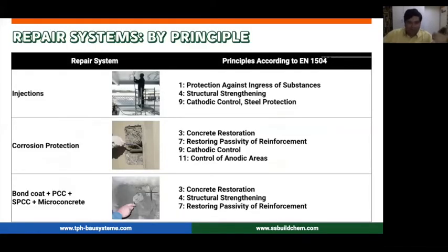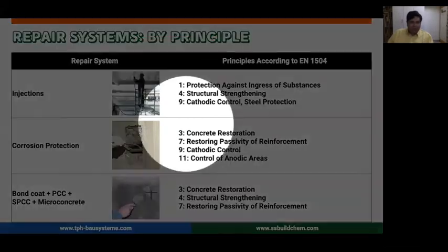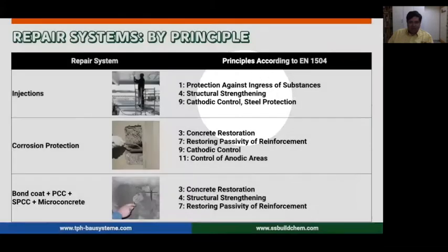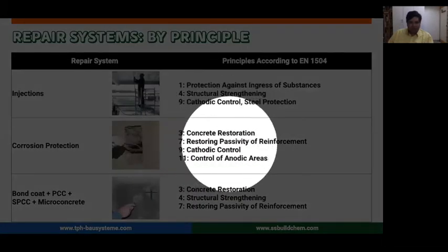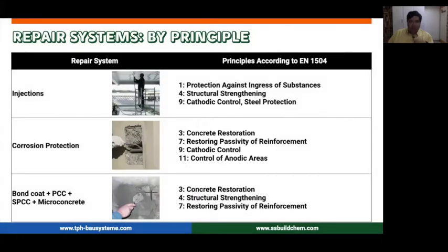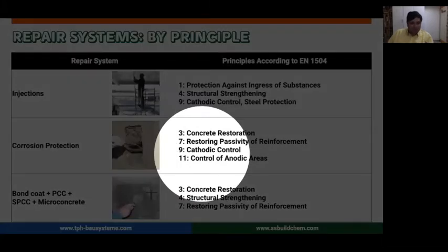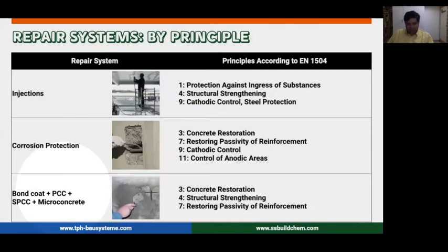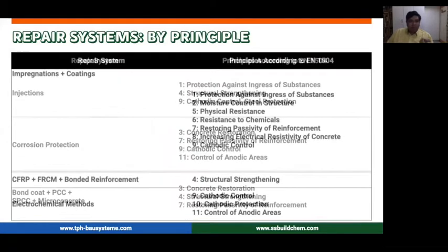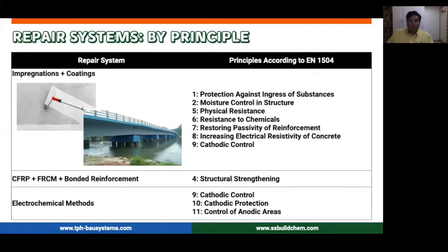So now again, if you take all those different steps that we just saw, what it would be coming into is mostly our injection systems, which can protect both against ingress of substances as well as provide structural strengthening. Then after the surface preparation comes your corrosion protection systems. This also meets a lot of principles according to EN 1504. Then comes your step on bond coat, PCC, spray polymer modified mortars, micro concretes, and so on. And followed last but not least by impregnations and coating.